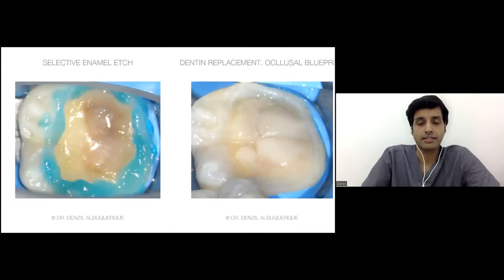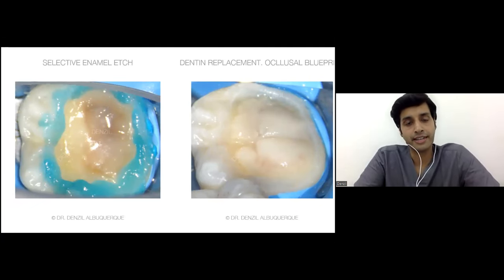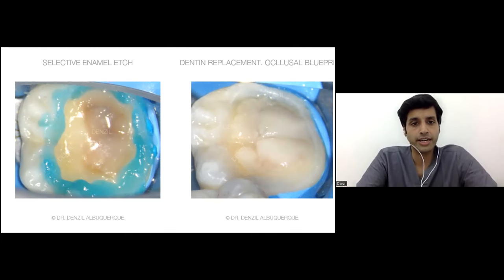This was a patient where ideally you would want to go in for an indirect restoration, but the patient was flying abroad within 3 days and the tooth was showing good signs of vitality. So we went in for a direct restoration. If there is a little bit of bond that might have flown onto the enamel, we can just roughen the enamel and then go in for the selective enamel etch, followed by dentine replacement.